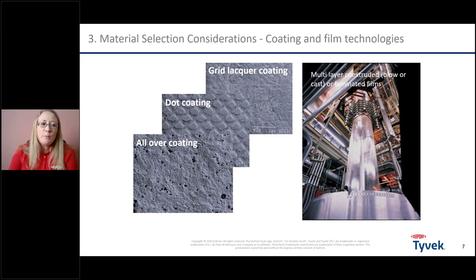In terms of Tyvek, you have principally three different coating solutions: a water-based or EVA-based all-over coating, a hot melt dot coating, or a grid lacquer coating, depending on the applications and the materials you want to seal with. Also, there are some differences in porosity, but all let sterilization gas through. Then you can also select, instead of the coating, a multi-layer peel film. It can be co-extruded or laminated, also depending on whether it's a flat application or a forming application. But it's important to consider the right materials to go together.